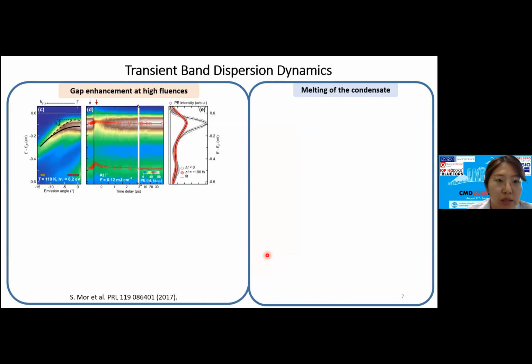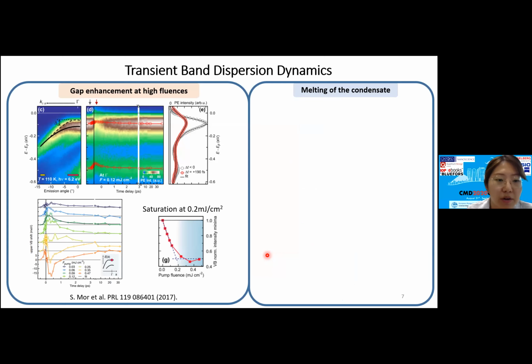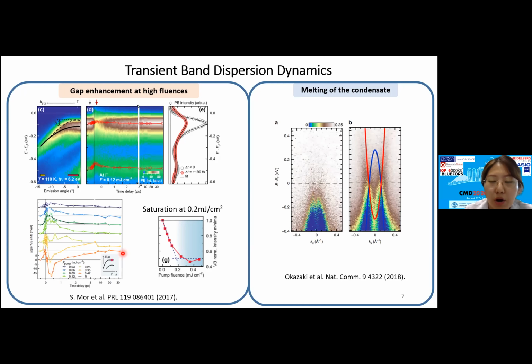The first paper is from Berlin, and it argued for band gap enhancement. When we pump hard enough, this valence band starts to get lower, which means the gap is opened more. But oppositely, the other paper from Tokyo University argues that when we pump hard enough, we can see the spectral weight pushed into the gap.